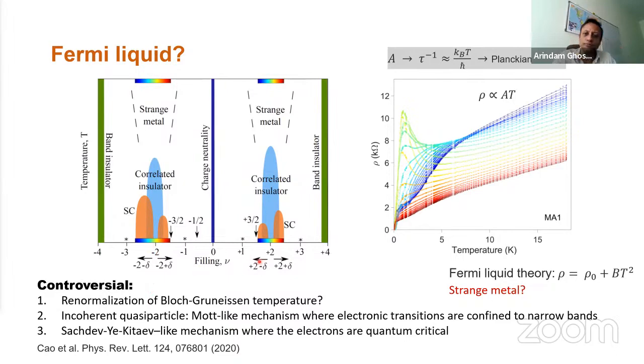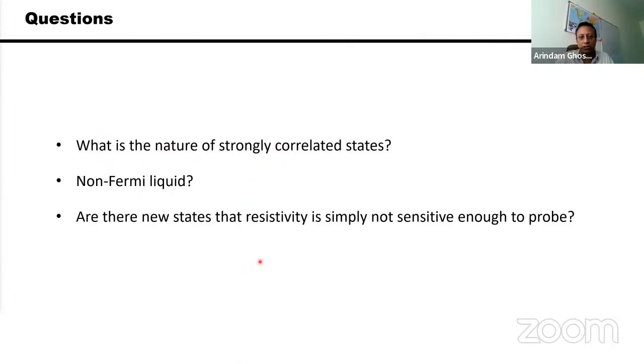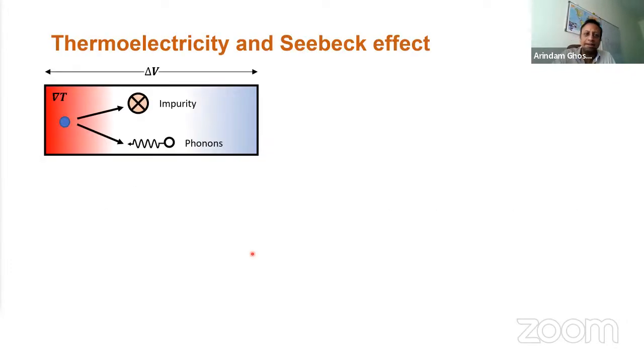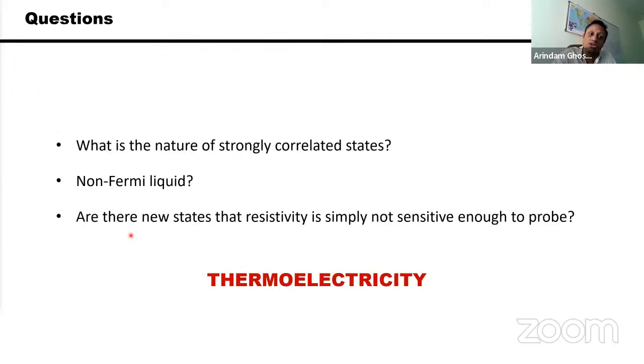So this is one of the key questions that arose when the filling factor of this twisted bilayer graphene is close to ±2. So we wanted to ask this question with our technique, and one of the techniques that we wanted to use is called the thermoelectricity technique. And the reason thermoelectricity was used is because it is an extremely sensitive probe to strong correlation effects, or effects when the usual electron and hole quasi-particles do not exist and they become ill-defined. So we wanted to ask if around the filling factors of 2, the quasi-particles that we have in our system are indeed like a Fermi liquid or conventional metal or not.